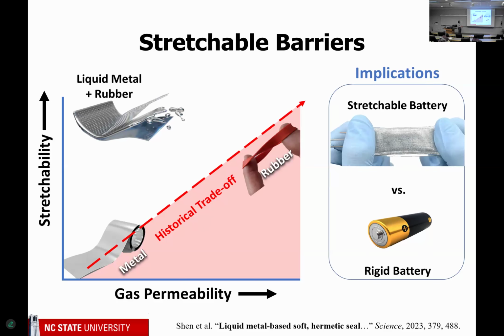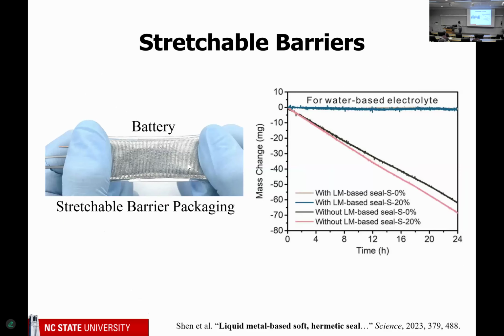Well, one example is batteries. So batteries typically come in these rigid containers. That's to keep the liquid inside and also to keep the oxygen, which is reactive, on the outside to not let it come into the battery and destroy it. So we made one of these, and you can see a picture of it here. This shiny stuff here is our liquid metal coating, and you can see the electrodes of the battery here. And we measured the mass versus time. We're not the first people to make stretchable batteries, but the dirty little secret is in other batteries, over time they degrade because the liquids on the inside just diffuse out. But with ours, the liquid metal coating basically is a hermetic seal. In fact, we had trouble measuring the permeability because it was so low. It was below the level of the instrument. So it's a really good stretchable barrier.